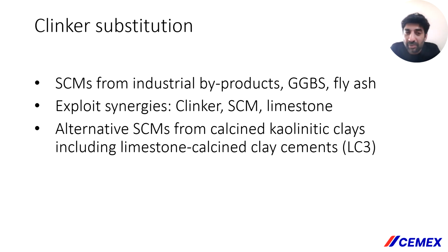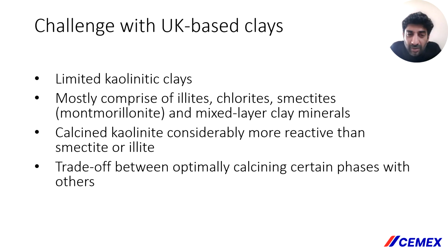Clays, on the other hand, are naturally abundant, and in many parts of the world, alternative SCMs from calcined clays are being developed at scale, including limestone calcined clay cements, known as LC3. Although kaolinitic clays are typically found in tropical and subtropical regions, the challenge with UK-based clays is that kaolinitic clays are less common here.